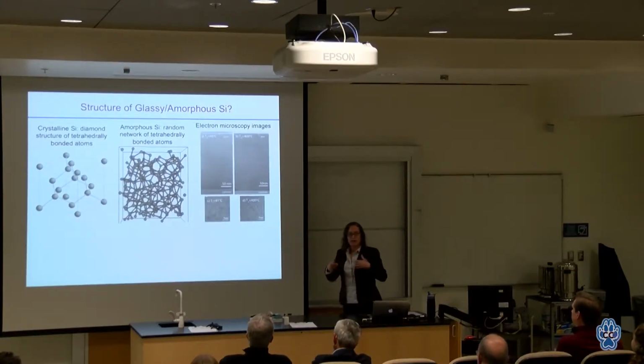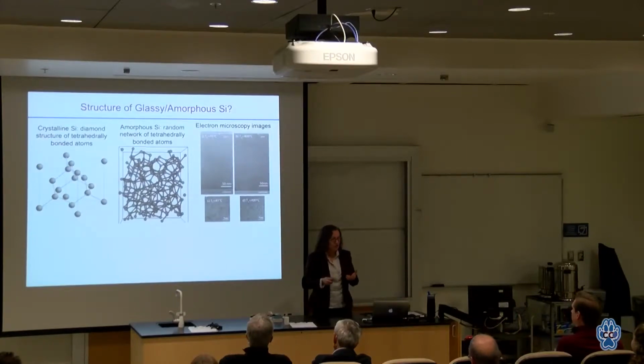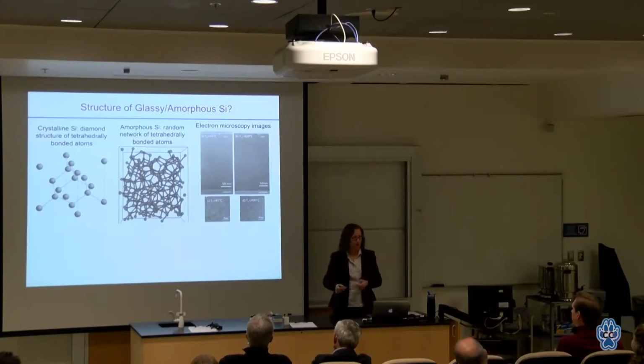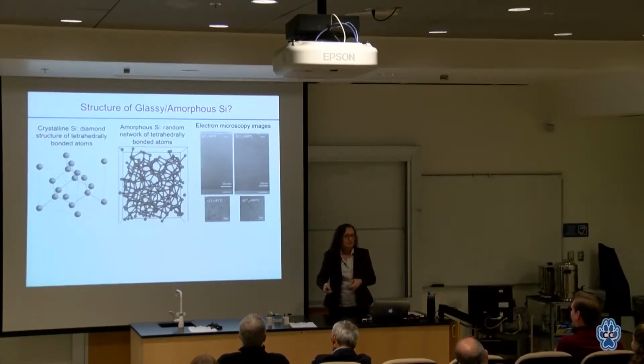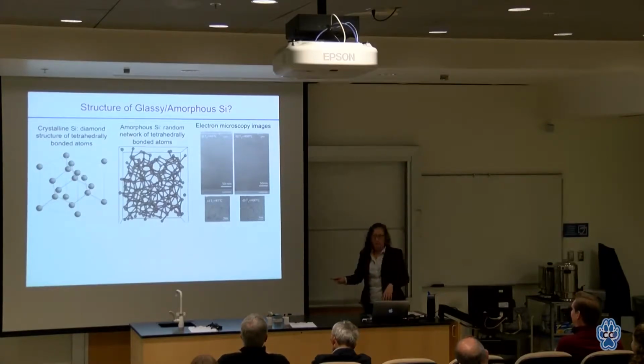And so one of the issues with the amorphous structure is everything is a big, broad distribution. So you're trying to look for subtle differences in big, broad distributions, and it's a painful process. So I'll come back to that point, but my only point here is really they look the same. So you have to be more nuanced in what you're looking at than just a bunch of images like this.